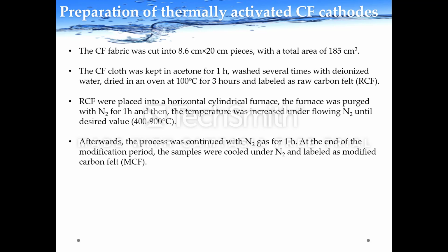What we made in this study: we bought carbon felt material, and we cut it with a total area of 185 square centimeters. Then we kept it in acetone for the washing process. Then we dried it in an oven and used it as raw carbon felt.